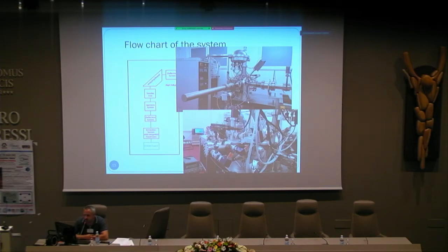We can also heat up the target. We can work in temperature ranges from liquid nitrogen temperatures up to 1000 degrees Celsius, and that might be useful for some of the materials. We also have a manipulator here that allows us to position our target as well as possible.